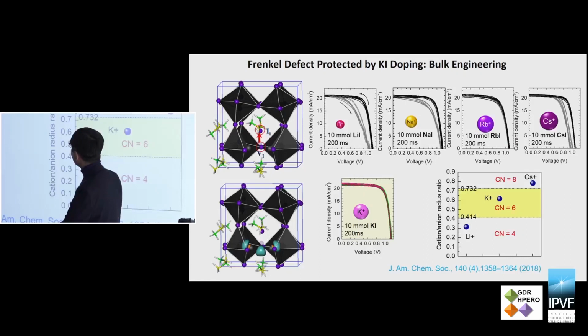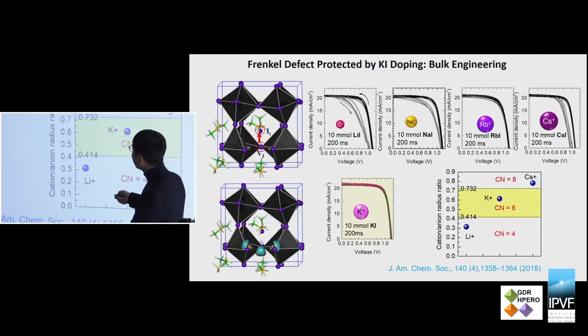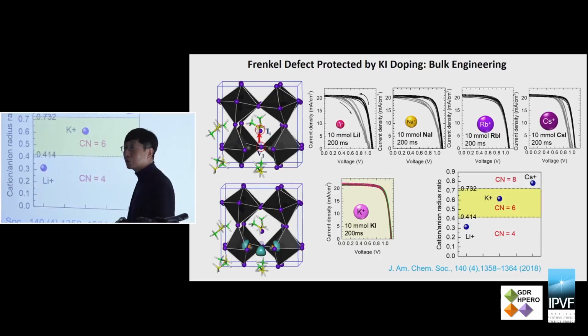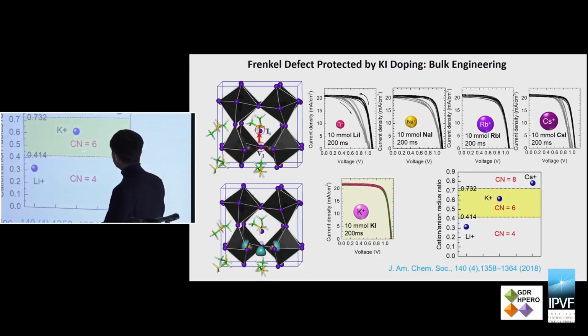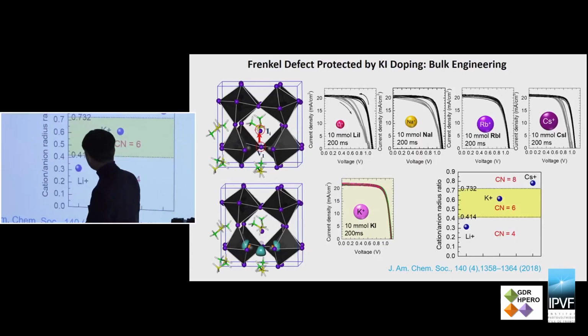So we found that small ones, or even sodium and cesium, do not work well, but potassium always works very well. This Frenkel defect site is related to octahedral geometry, and potassium is suitable for the octahedral geometry. So potassium is working well. We published this work in JACS in 2018, and then we wanted to investigate further what is going on with the ion migration if we add the potassium ion here.